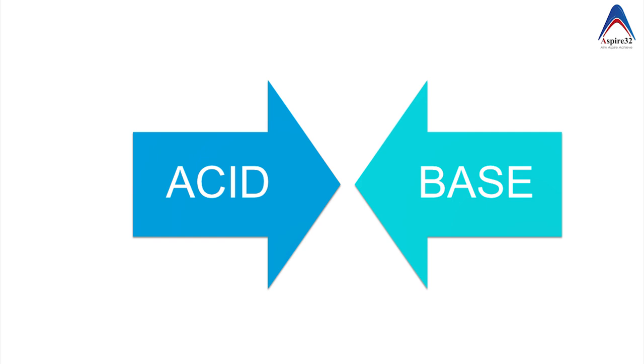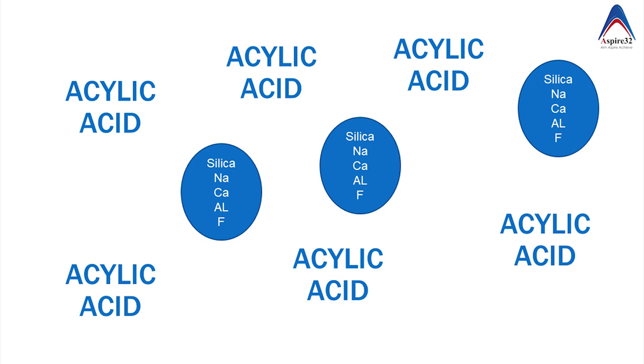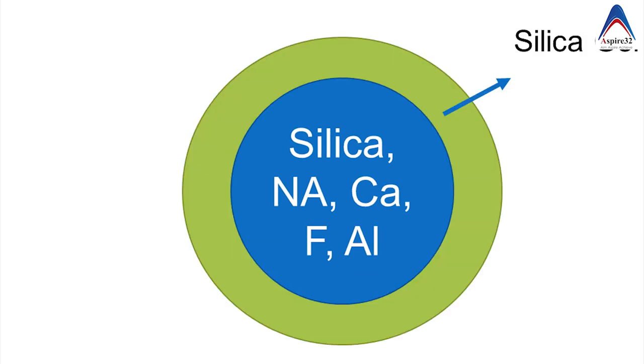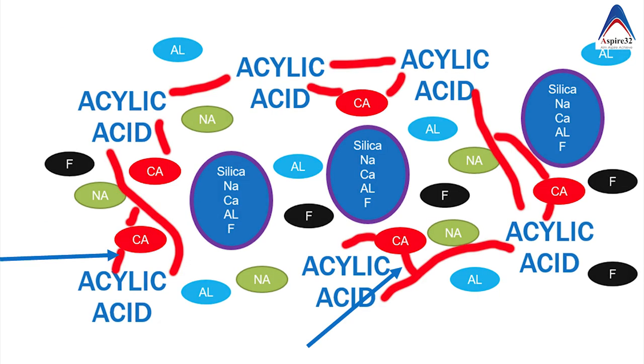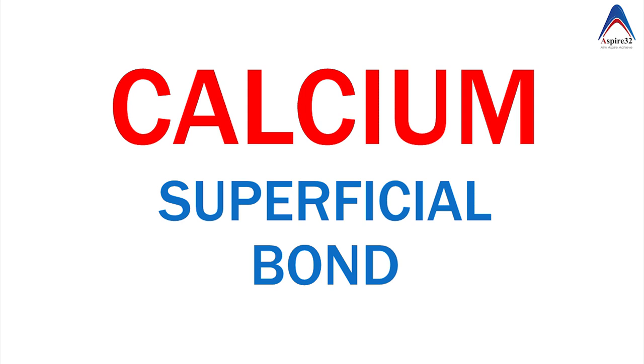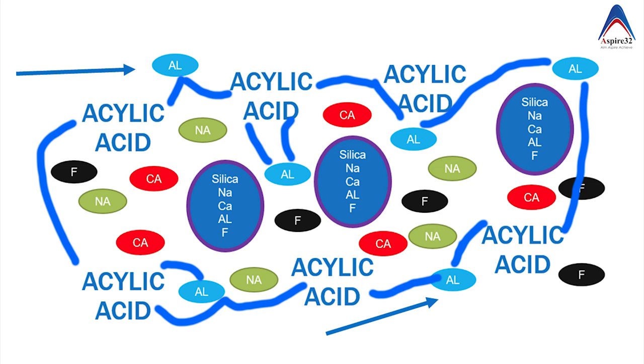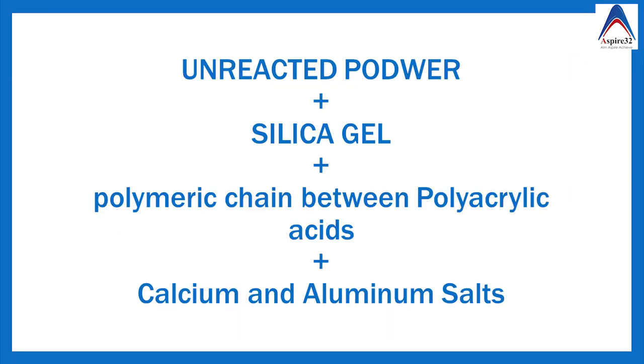The conventional glass ionomer cement sets because of an acid-base reaction that starts when the liquid attacks the powder particles. The acid dissolves the surface structure of the basic powder, forming a silica gel. The ions in the powder — aluminium, calcium, sodium, and fluoride — start getting leached out into the matrix. Initially it is calcium that bonds with the polyacrylic acid, but since the bond is weak, it is soon replaced by aluminium ions within the next 24 hours. Sodium and fluoride do not take part in the setting reaction; the fluoride is available for anticariogenic activity.